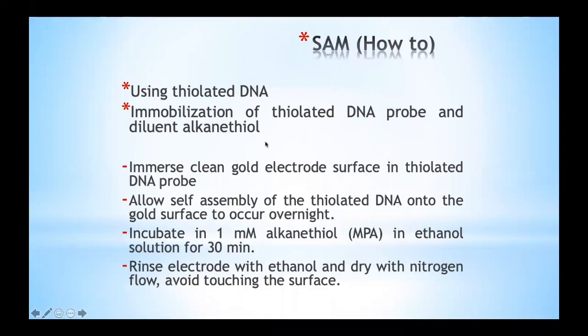This is the protocol that you can use to do the self-assembled monolayer process. First, by cleaning the gold electrodes and incubating the gold electrode in thiolated DNA probe. Further incubation with alkane thiol as the surface or substrate passivation, followed by rinsing or washing.